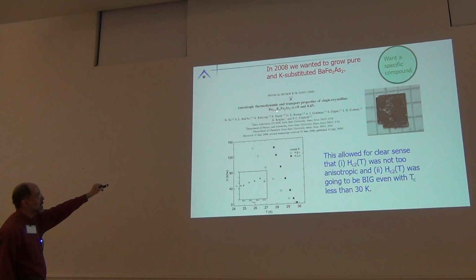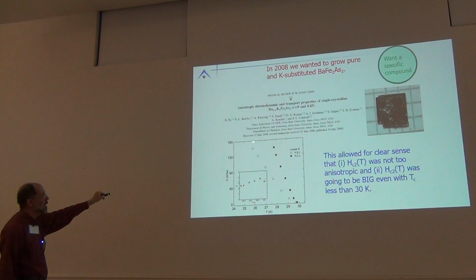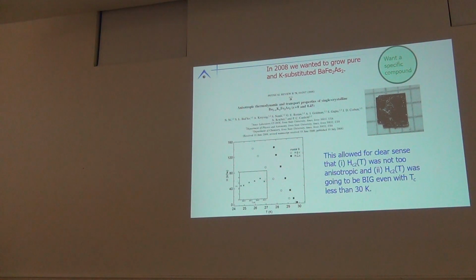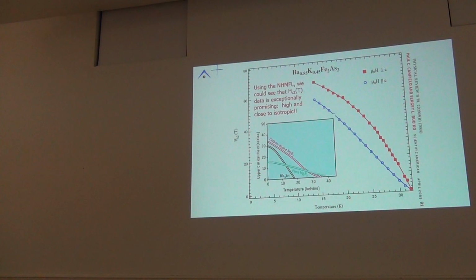Okay? We could substitute in potassium, get it to superconduct with a single crystal. You can measure anisotropic properties. Here's the anisotropic HC2 up to 14 Tesla, the field we have in our laboratory. And what's remarkable is 14 Tesla, which is not a small field, only suppresses TC from 30 to about 27, maybe 26. So HC2 is going to be big. In addition, it's looking fairly isotropic. Yes, isotropic. We went to the National High Magnetic Field Lab.